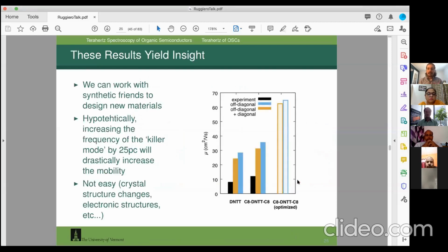What we found was that if we hypothetically increase the frequency of that one vibration, of that longitudinal vibration, we increase the predicted charge carrier mobility by quite a bit.